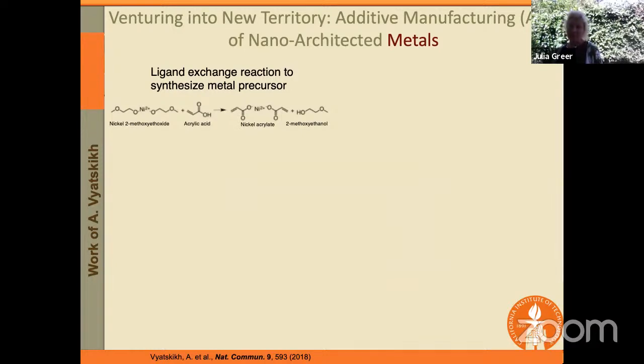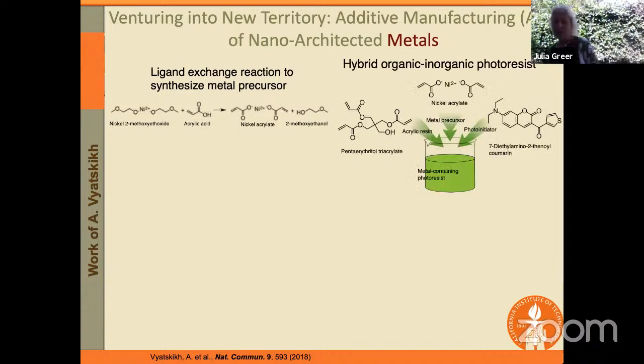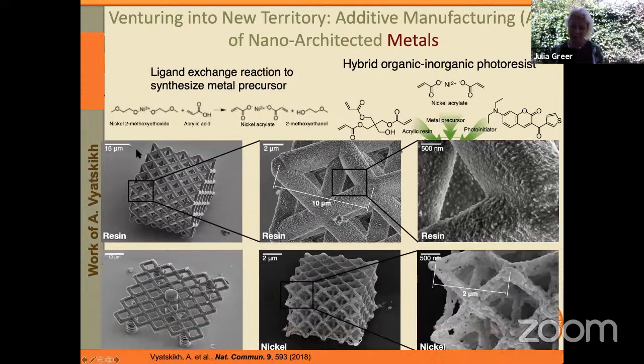As we've been working with these architectures, what we found ourselves doing is that we can explore the different chemistries and the resins that we put together when we manufacture these materials. And instead of buying the commercial resins, we can start synthesizing them ourselves. So this is the work of my former student a couple of years ago. What you can see is that this nickel ion is now captured inside of an organic outer shell. So the nickel ion is at the core, and now you have this organic shell. And when you undergo this acrylate-based reaction, where you effectively cross-link this polymer in response to the laser light, what you end up with is an architecture that I'm showing you here that contains nickel.